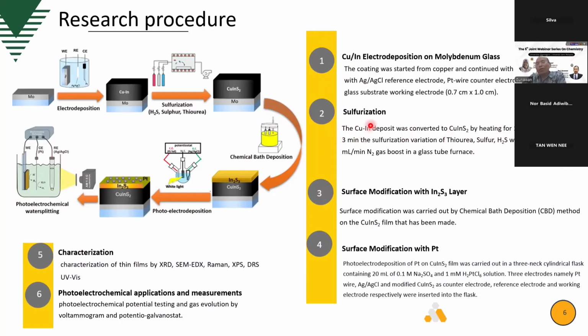So for sulfurization, we use 10 minutes at 400 Celsius. After 3 minutes, with variation of thiourea, sulfur, H2S was flown with 200 milliliters per minute of nitrogen gas in a glass tube furnace. So we use a glass tube furnace. And then by chemical bath deposition, we can deposit the indium sulfide on the copper indium sulfide.